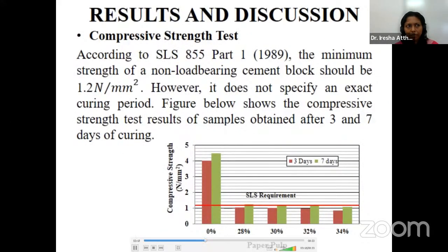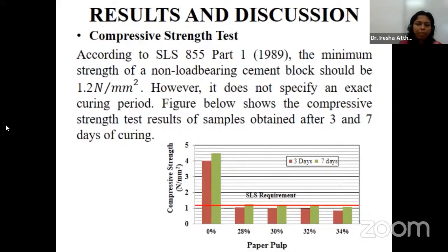This is the time for results and discussion. First, let's see the compressive strength test. The blocks were tested for compressive strength according to SLS 855 Part 1, 1989. Individual blocks were cured for 3 and 7 days before being taken for testing with a compressive strength testing machine. According to SLS 855 Part 1 of 1989, the minimum strength of non-load bearing cement block should be 1.2 Newton per millimeter square. However, it does not specify an exact curing period. This figure shows the compressive strength test results of samples obtained after 3 and 7 days.